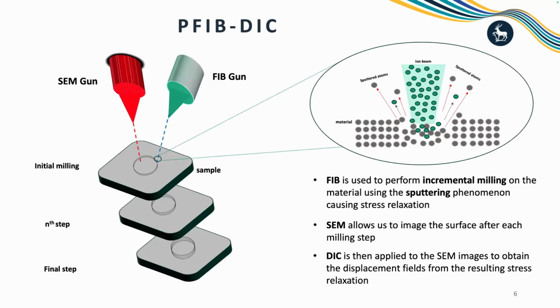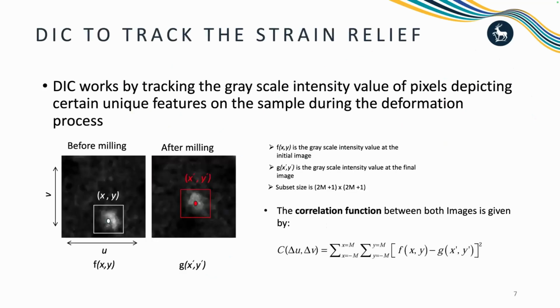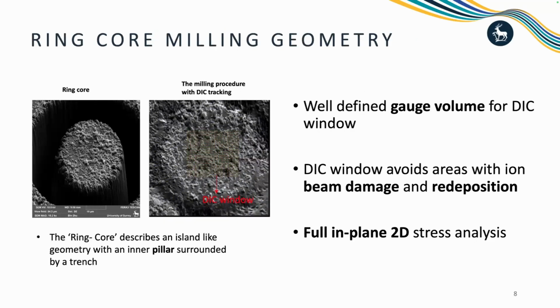And after each milling step, we use the SEM to take images and record the stress release procedures. Then finally, we use DIC to analyze the stress release and achieve the measurement. And here is the basic mechanism of how DIC works. The software or algorithm checks the similarity in this window and then calculates how the material deforms during the stress release.